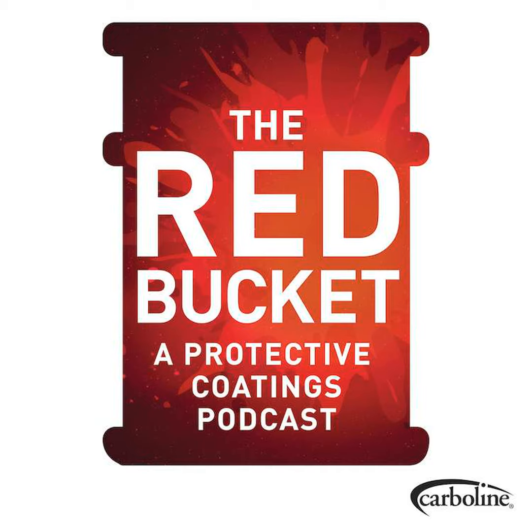Typically, what I see is the substrate starts to develop corrosion pitting, where pits can typically be very, very sharp and deep. So during the cleaning process, you have to get an inspection done to see how much steel loss is there, and typically there is going to be steel loss. So now you have to build that back up by some type of mechanical repair. Mechanical repair gets us to where we wound our way to one of the subjects of this, which is blending, the term blending.